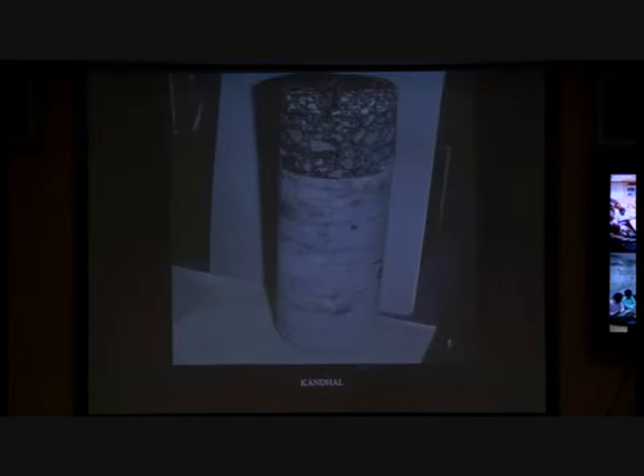So here is a typical reflection crack. Actually we don't know, there is a cement concrete underneath, so we don't know whether it's a thermal crack, which is also transverse, or whether it's a reflection crack due to a joint in the concrete. So if you take a core at that point, in this case you can see the crack in the bituminous concrete, but there is no joint in the concrete underneath. So most likely that crack in the asphalt concrete is a thermal crack. So you can find out pretty quickly.